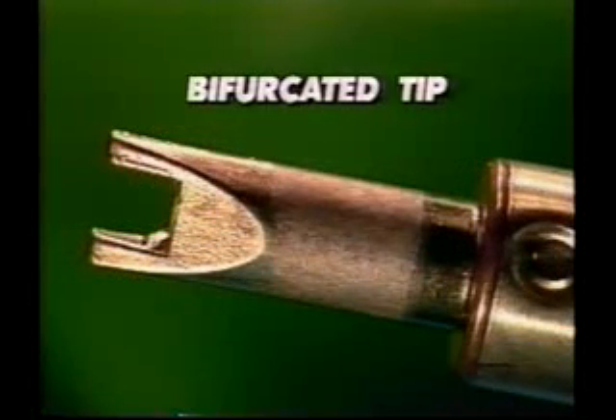If the iron starts to push on one side of the component as the opposite solder joint begins to solidify, the pressure can cause the land to separate from the circuit board. Some technicians use two soldering irons to remove chip components. This technique can overcome some of the problems we just mentioned, but it does take considerable skill to properly align both tips without touching anything else. The first recommended method for removing chip components uses a bifurcated or forked tip with a hand soldering iron.